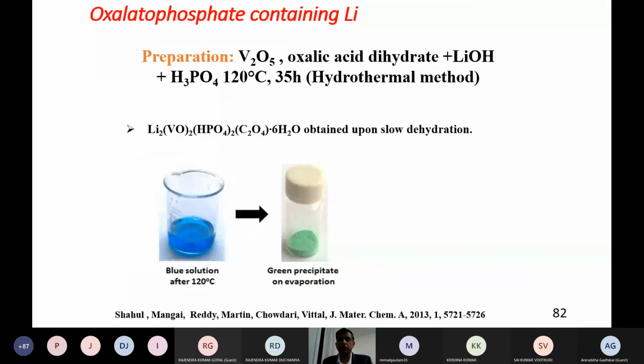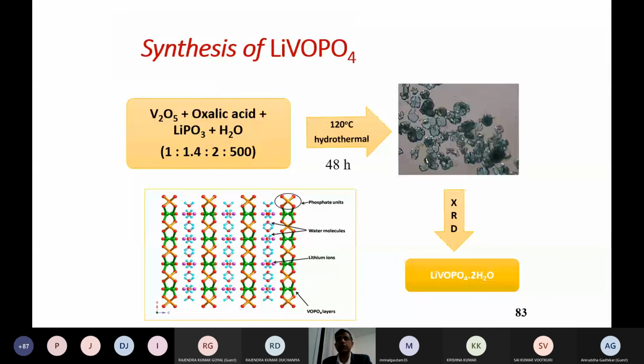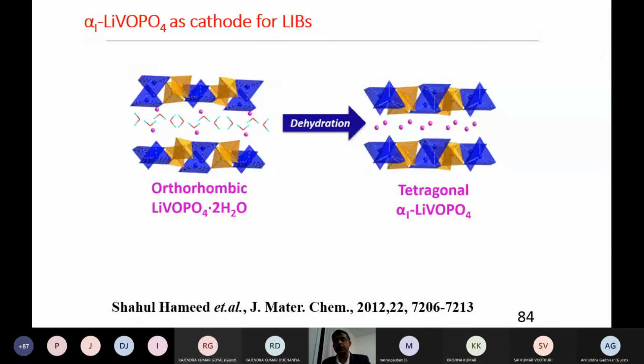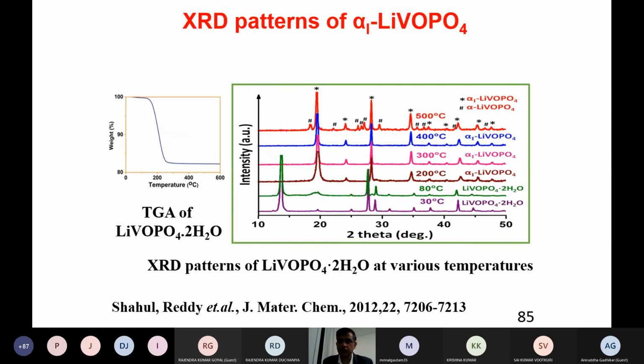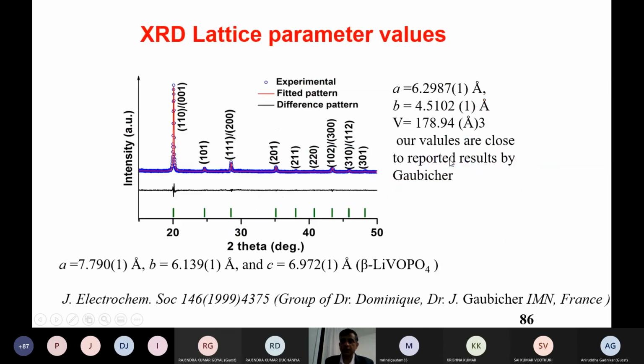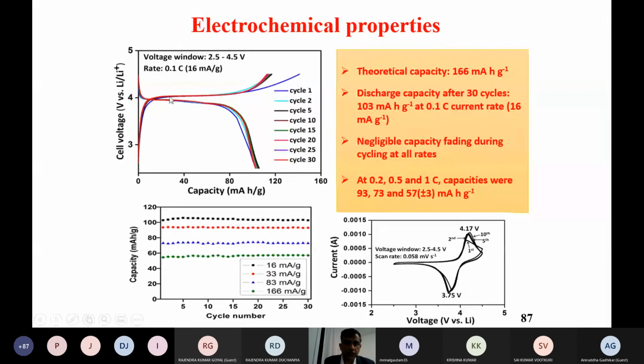That's the way you can do. And another, containing vanadium phosphates. In fact, these are new compounds we can prepare hydrothermally. The idea here is that we can see the phase transformation from the orthorhombic to the tetragonal phase. The beauty of these compounds is that interestingly we can get nearly 4 volts potential. These are the lattice parameters I discussed, and you can see the nearly 4 volt potential we can get, and reasonably good stability, nearly around 110.